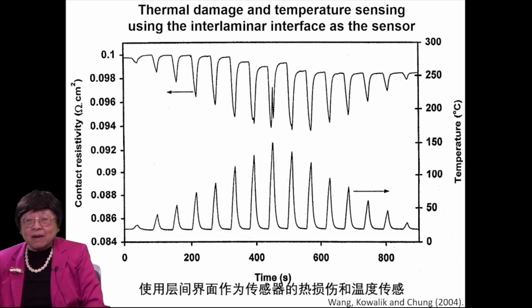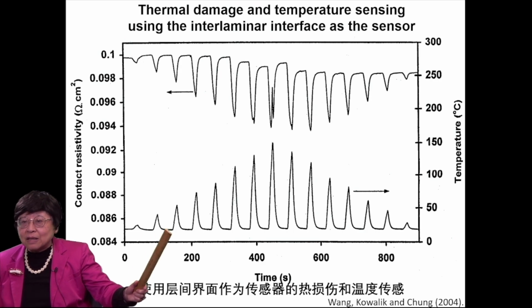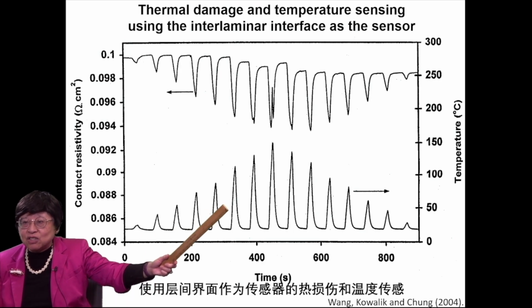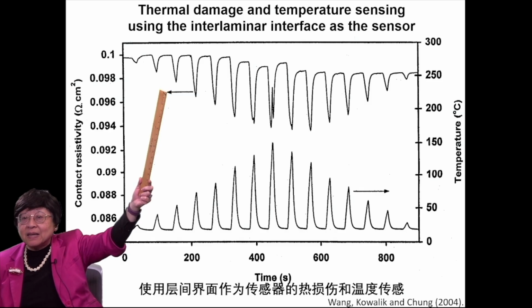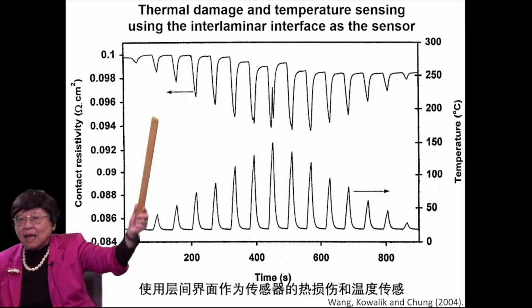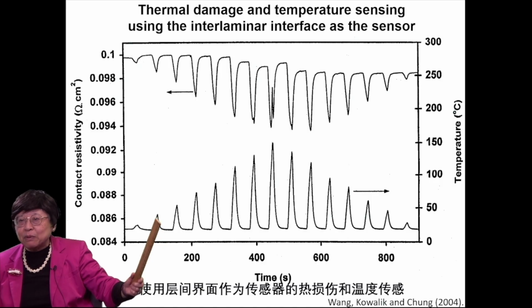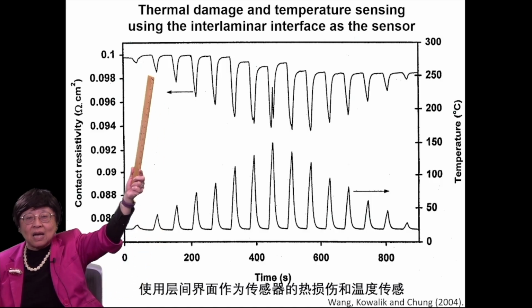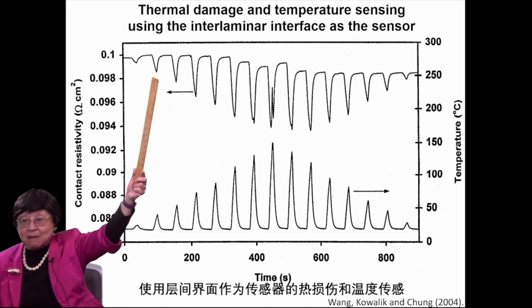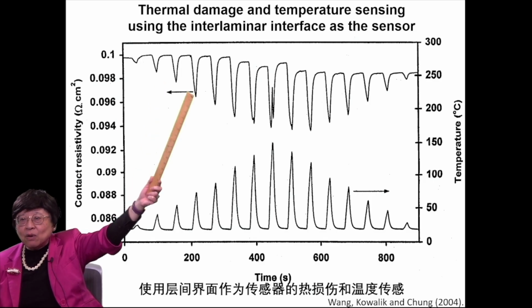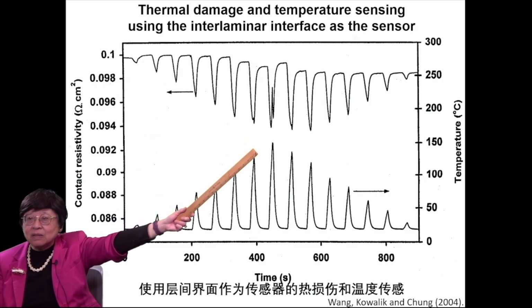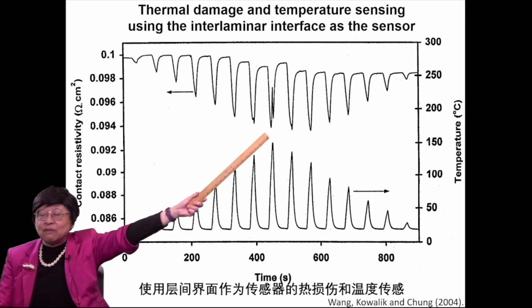We can also monitor thermal damage as well as the temperature at the same time using this interface as the sensor. Shown at the bottom is the temperature variation, and up here is the variation in the contact resistivity of the interface. Every time one raises the temperature, the contact resistivity goes down, as I mentioned before. But note that at the highest temperature, the contact resistivity shoots up,